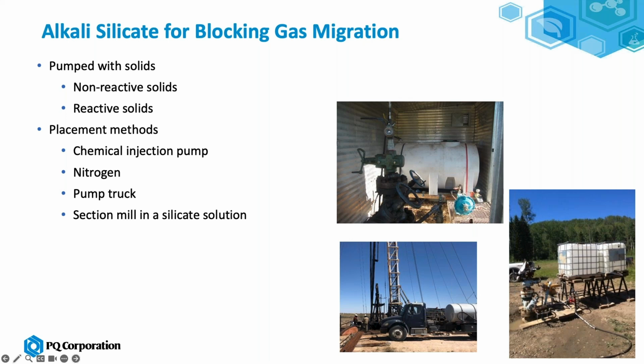Alkali silicate usually with the cement pumped and then spacer, and then followed by the cement. The other option for placing silicate, and this has been documented and shown to be highly successful, is to section mill in a silicate solution. So you're generating fines, that creates a matrix, and then that helps seal the pathways and imparts strength. Next slide.